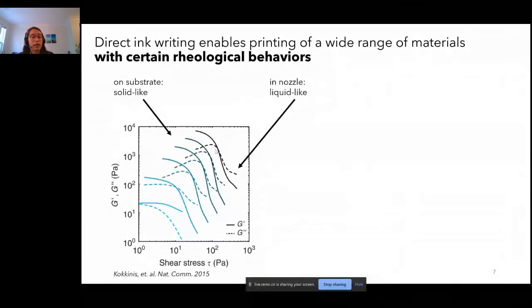Inside of the nozzle, we're going to be at high shear stresses, and you can see that G double prime is greater than G prime, so this material is going to behave like a liquid. And then in between that solid-like to liquid-like transition, there is a yield stress. That's the stress at which this material stops behaving like an elastic solid and starts to behave like a liquid. That yield stress needs to be high enough that the material won't just collapse under its own weight. It won't just flow onto the substrate if you bump the stage or move the stage around.